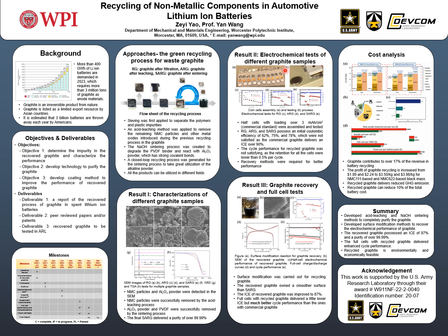However, the electrochemical performance of the recycled graphite is not satisfactory. As shown in figures C to E, the recycled graphite samples delivered much lower initial Coulombic efficiency and stability compared to the commercial graphite, which will lead to lower energy and shorter cycle life in practical usage. So a recovery process is essential, and let's come to the recovery part.